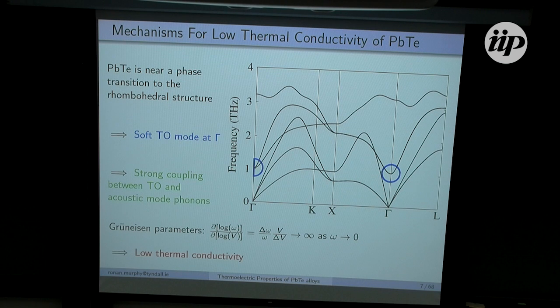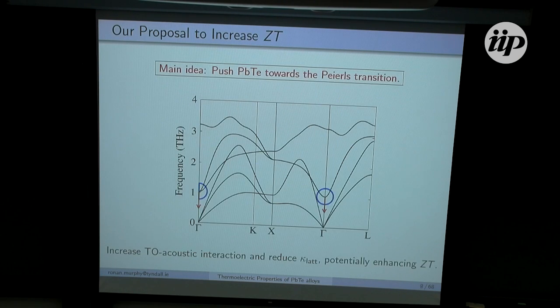But that's all well and good. The question is, what can we do with that? So the idea I want to talk about here is we want to take lead telluride and push it towards the phase transition. This will soften that TO mode at the gamma point, increasing that TO-acoustic interaction, reducing the phonon lifetimes, and reducing the lattice thermal conductivity. And then hopefully we get quite a nice boost to the thermoelectric figure of merit.